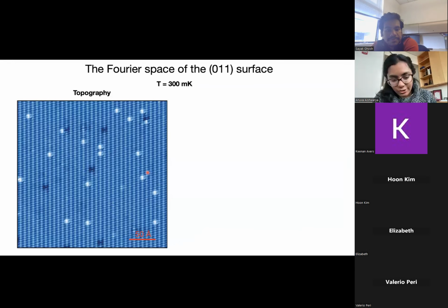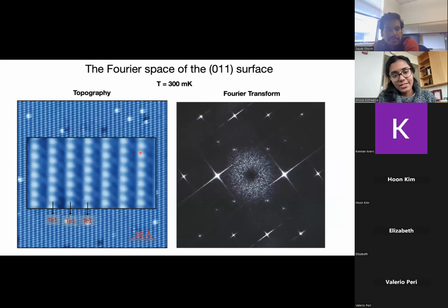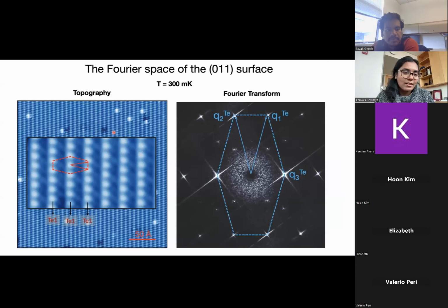Now, we can also look at this surface in Fourier space. I have rotated the topography so the chains are along this direction, and this is the crystallographic a direction. This is a topography taken at 300 millikelvin, and if I take a Fourier transform of this, this is what we see. First of all, we can identify the Bragg peaks that originate from the atomic sites. This is a strange squished hexagonal shape, and that's because the lattice is also a bit strange.